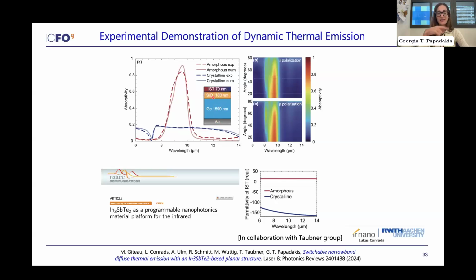SiO2 has an emission resonance at 10 microns. So this device is very resonant when you put on top of it a dielectric material, a transparent material in the mid-IR. What we put on top is IST, a phase change material that has this dielectric response. In its amorphous phase, it's dielectric and transparent, but in its metallic phase, it's reflective. So when I change the phase of IST, it becomes very reflective, and no emission or absorption is possible.